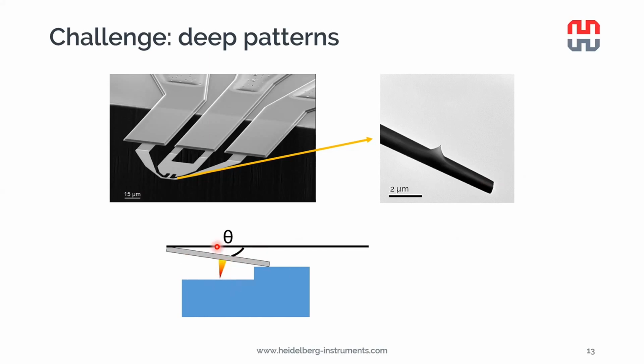We apply a small angle, and from this geometrical consideration presented here, we can see that the maximum patterning depth we can achieve in the PPA resist is not more than 250 nanometers in any case. We can also etch the structures into silicon to achieve deeper patterns. But the PPA selectivity against silicon is typically in the range of 3 to 5, and with some super nicely optimized process, we can achieve maybe amplification in the range of 10, but not much more than that. So that gives us a maximum pattern depth in the range of a few micrometers.